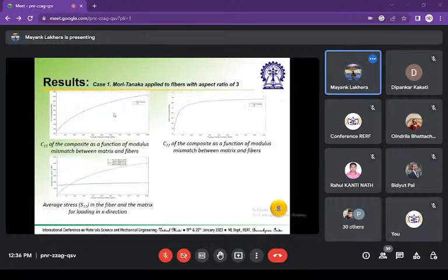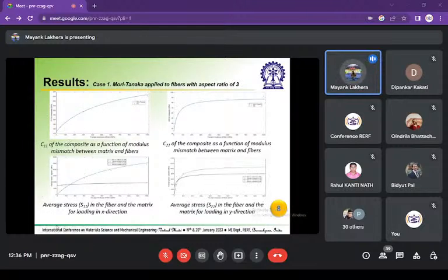Okay. So for results, we can see the C11 and C22 of the composite. There is a clear match between the FE results and the Mori-Tanaka formulation, and there is an exact match. There is a very close match for average stresses in the fiber and the matrix, and for the average stresses in the S22, there is some gap at higher aspect ratio for fiber and the matrix.